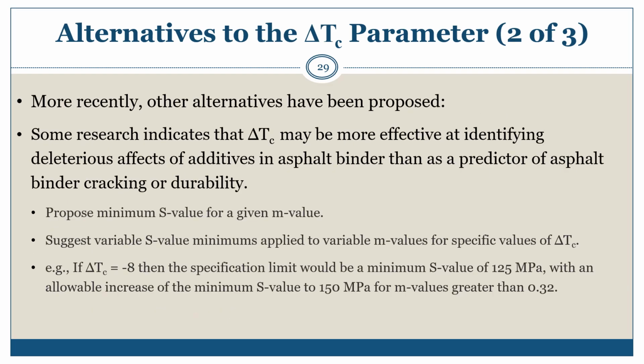More recently, ongoing research indicates that the delta TC parameter may be more effective at identifying effects of deleterious additives in asphalt binders than as a predictor of asphalt binder cracking and durability. Like the minimum S suggestion, this research prefers a minimum S value for a given M value, except for incorporation of modeling concepts to suggest variable S value minimums applied to variable M values for specific values of delta TC. This may sound complicated, however, it's quite simple.